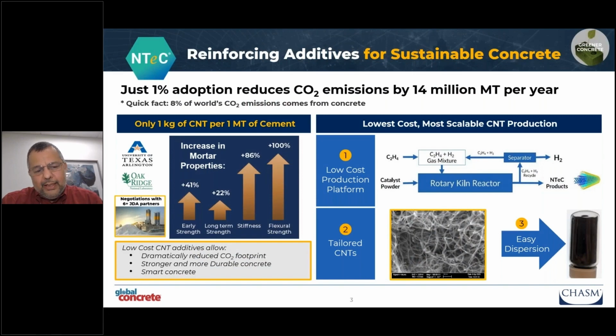So in short, why concrete? It's been long known. In fact, concrete was almost one of the first applications nanotube was tried on. It was known that if you disperse it well, you get very good early strength. And these are mortar-level tests reported by our university partner. You get long-term strength, you get high stiffness on mortar, and flexural strength literally doubling. And this was amazing. However, this could not be translated directly to the industry.